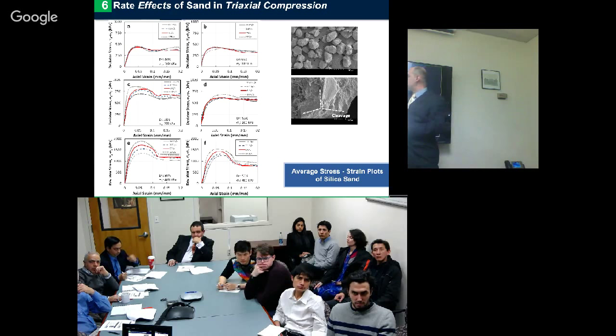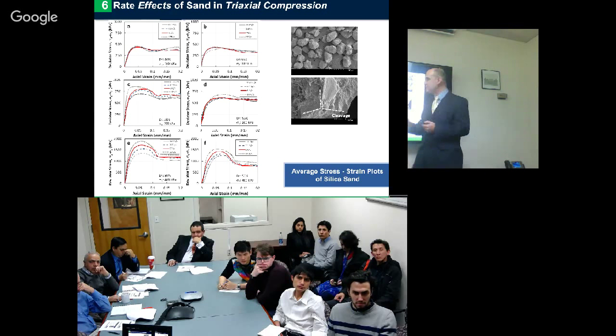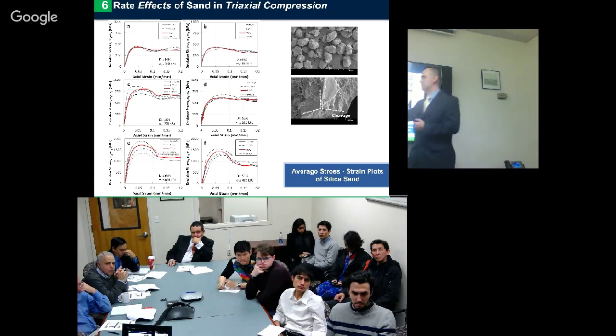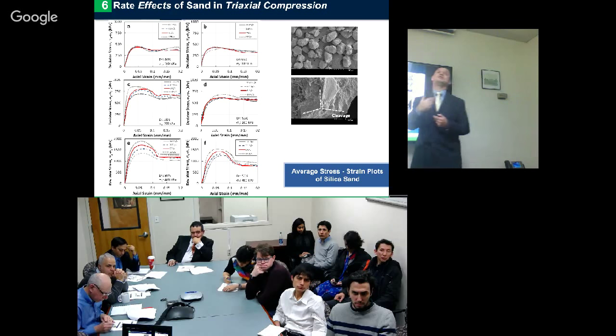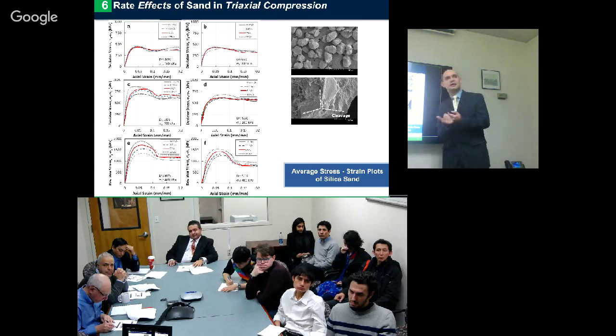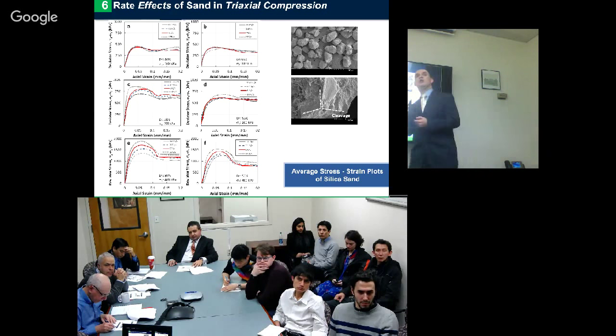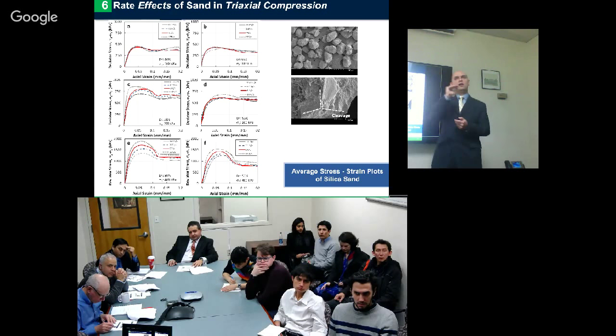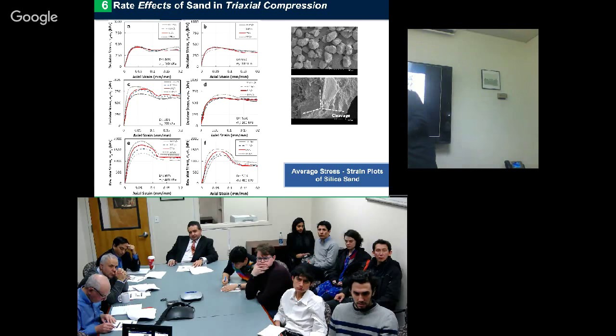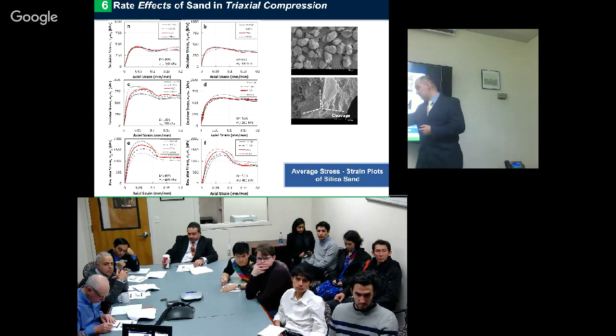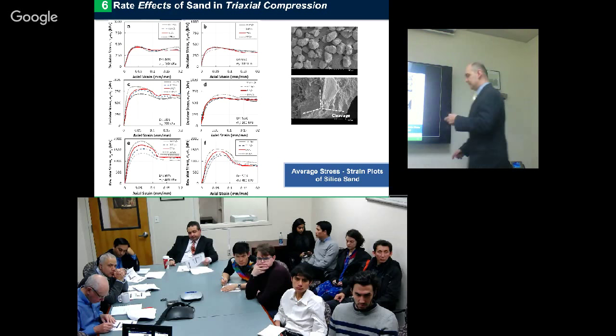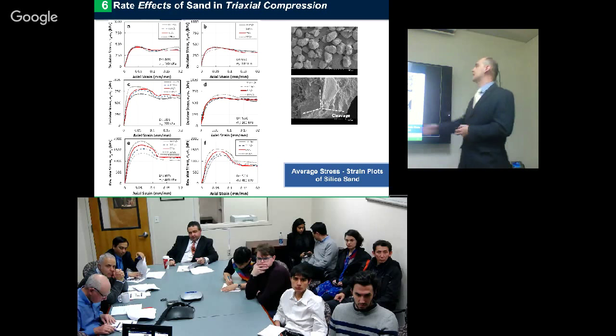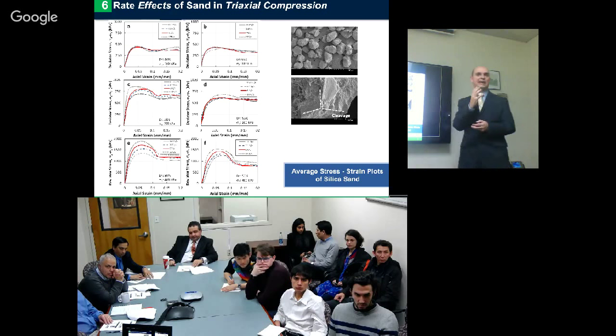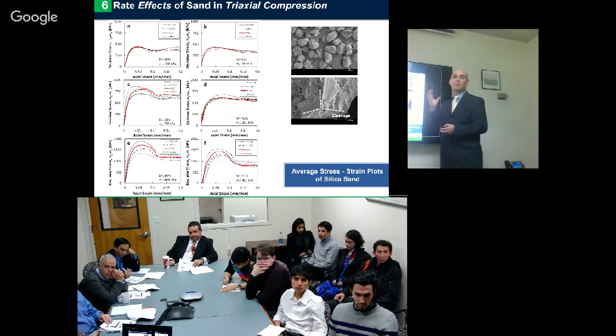We don't see much here either. We start looking at some small effects, but they are still not really well defined. The same here. And now, when the sample is loaded at higher confinement stresses, we start looking at something interesting, which is a well-organized trend where the slowest rate is going to be at the bottom, and the fastest one is going to be on top. It's more evident when the density is higher than when the material is loose. So this material is a siliceous sand that has these shapes, and that has some sort of well-defined cleavage when the particle is broken.